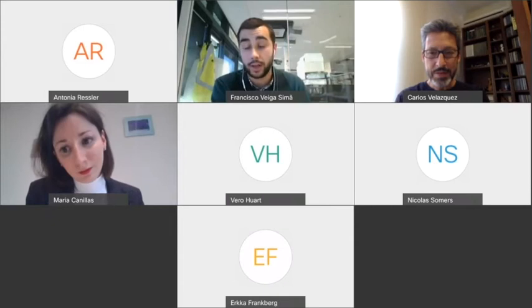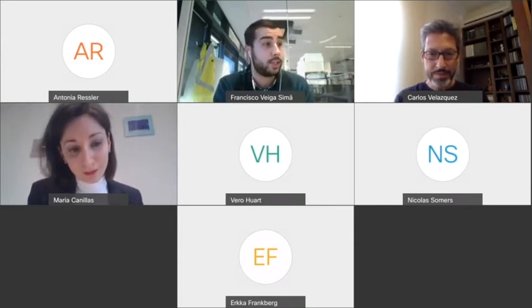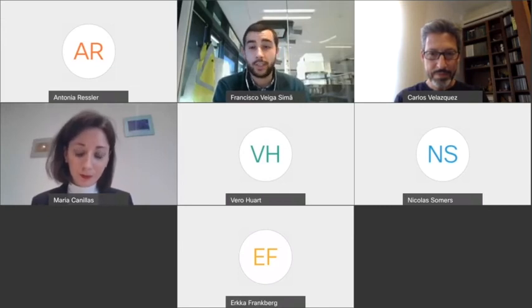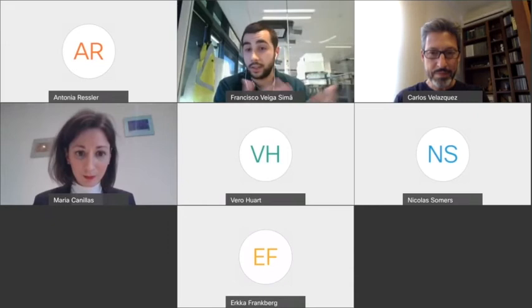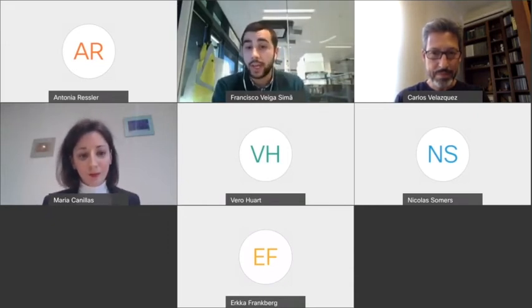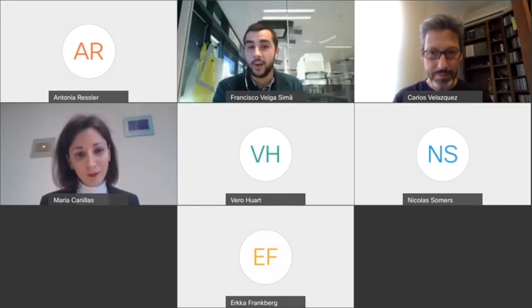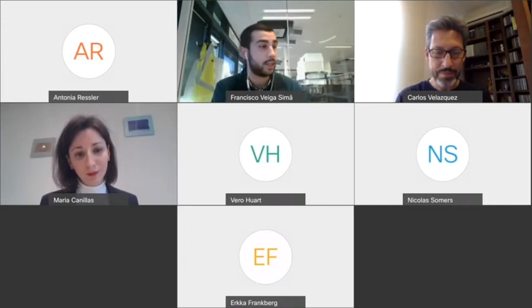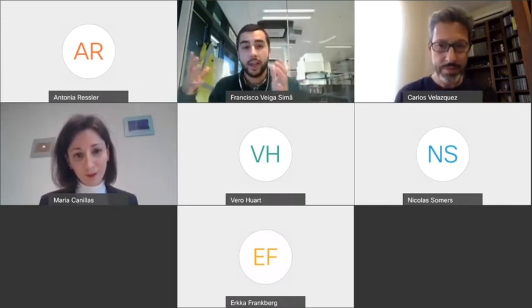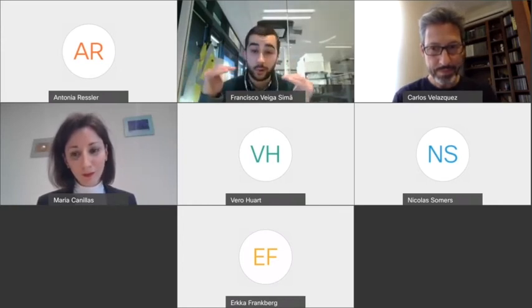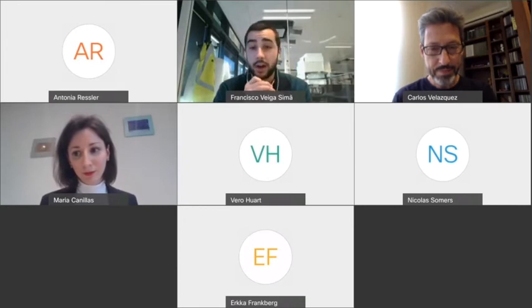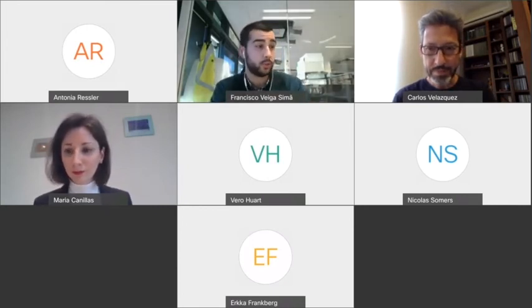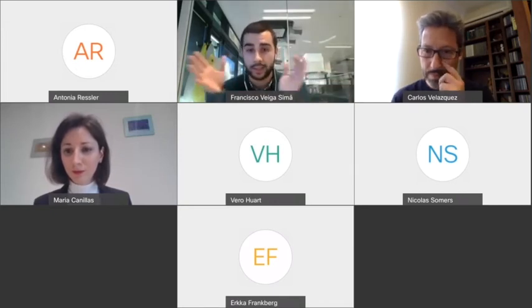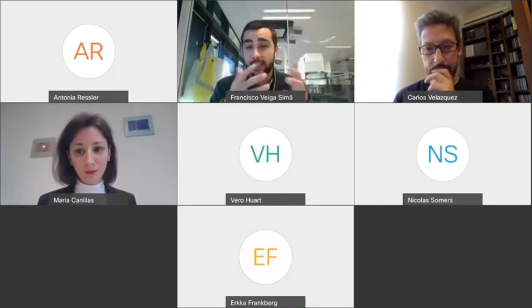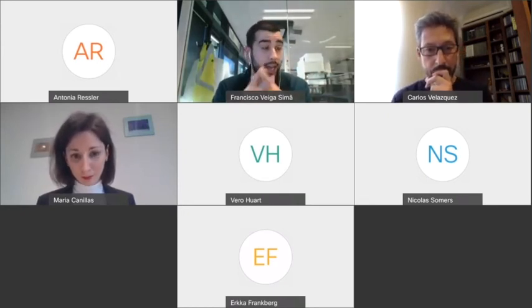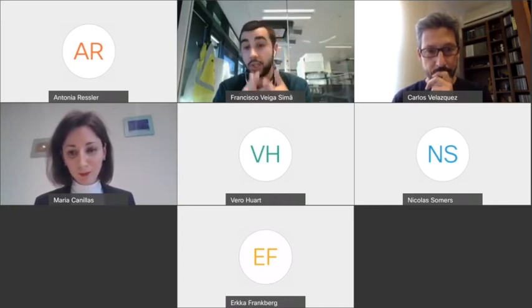And of course, the capillary flow of these species also plays a role in showing these crystals, this calcium sulfate, gypsum if you want. That's why when you look at buildings, you sometimes see some marks on them, because sometimes it's really hard to control all this, because a lot plays a role, the chemistry and the physics of the material. So of course you have to lower the levels of carbon and sulfur, which can also contribute to this. But definitely, in short, it is the calcium oxide reaction with the sulfate content that creates this calcium sulfate, which by capillarity reaches the surface, and which is soluble, of course.